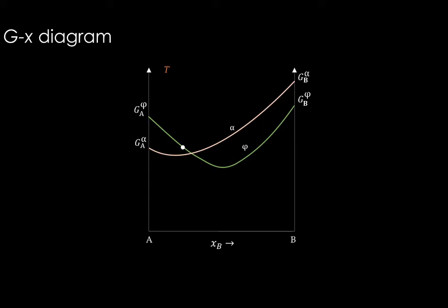Here we have the composition in phi structure, the phi phase. Is it the stable phase? Draw a tangent to this green line and see whether there is anything below this line. Yes, there is something below this line, right? Which means this is not the stable state. There can be something lower than this. Imagine this point. Is this the stable state?